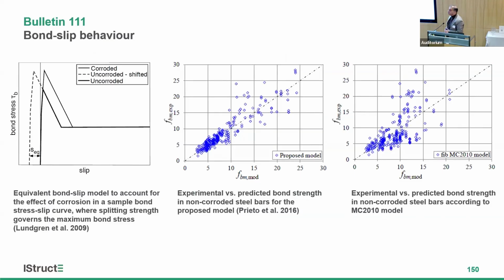Moving on, bond slip behavior is a big challenge. This is an example of a graph from our colleagues in Chalmers, who did a lot of work on corroded bond behavior, the impact of corrosion on bond slip behavior of bars, essentially plain bars or bars with ribs, with and without confinement. They did a lot of different tests. The simplified version brought into this bulletin starts from the original bond slip based on the Model Code 2010. Essentially they shift it back and reduce the maximum bond strength.